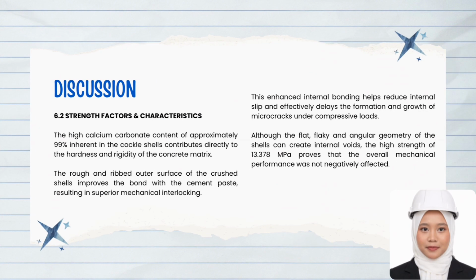For the strength factor and characteristic, the high calcium carbonate content of approximately 99% inherent in the cockle shells contributes directly to the hardness and rigidity of the concrete matrix. The rough and ribbed outer surface of the crushed shell improves the bond with the cement paste, resulting in superior mechanical interlocking. This enhanced internal bonding helps reduce internal slip and effectively delays the formation and growth of microcracks under compressive loads. Although the flat, flaky and angular geometry of the shells can create internal voids, the high strength of 13.378 megapascals proved that the overall mechanical performance was not negatively affected.